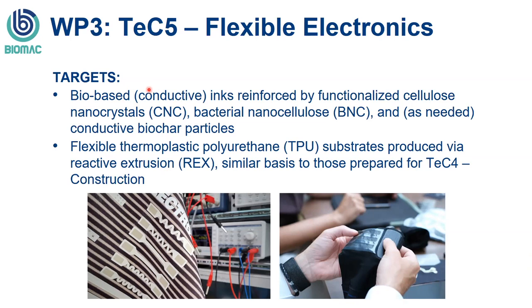And then what you can do is tap that layer to fabric, as shown here, so that you now have wearable flexible electronics. So the base layer is something that you can almost iron on or thermally bond to the fabric. And on top of that, there is also a printed layer of bio-based conductive inks, in this case, including functionalized cellulose nanocrystals for mechanical reinforcement. Bacterial nanocellulose also can be used this way, and conductive biochar particles for the conductivity. And of course, when we want a non-conductive ink, we simply remove the biochar. We just use the mechanical reinforcing additives as needed, and we can have a non-conducting system as well.